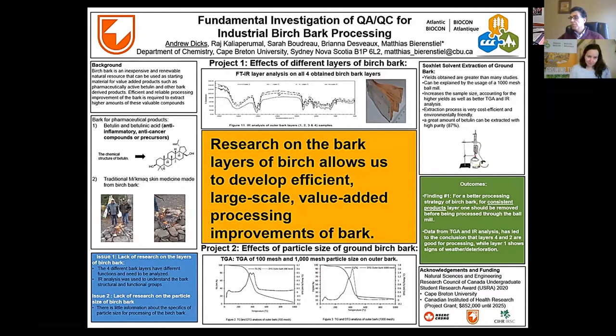For project two, the effects of particle size of ground birch bark, we used TGA of 100 mesh and 1,000 mesh particle size on the outer bark. What we realized is that the 1,000 mesh has a larger surface area and finer particles, and it will react much better. We also realized that after 400 degrees Celsius, major things start to break down. And between the 100 mesh and the 1,000 mesh, the graph showed a different peak. And so we realized the 1,000 mesh is better.